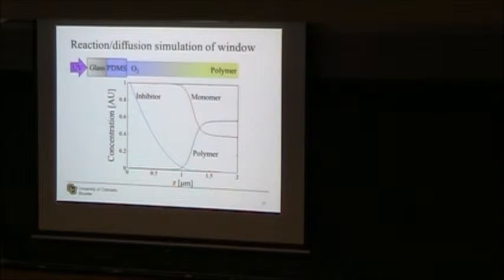So in normal systems, for example, if you expose a grating, you can only get transverse diffusion because axially everything is the same. You have no concentration gradient axially. Where here, I do have a concentration gradient axially, and so I can diffuse large transverse structures now.